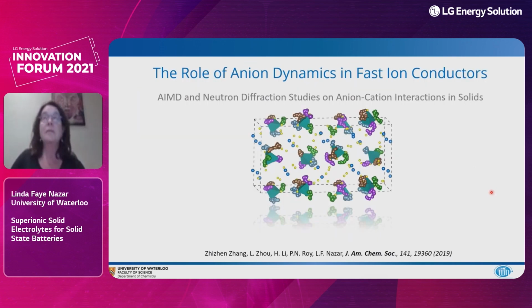So I'll start off with the somewhat, I would say, intriguing concept of the role of anion dynamics in fast ion conductors. And we started this first with this sodium ion conductor, Na11Sn2PS12, that we published in JACS. What you see here is a picosecond snapshot of the PS4 anions in this lattice, and you see the trajectory. This is from an ab initio molecular dynamics simulation. So you see the trajectory of the sulfide as this polysulfide rotates on its position in the unit cell. And this is commensurate with the mobility or the migration of the sodium ion in the cell.